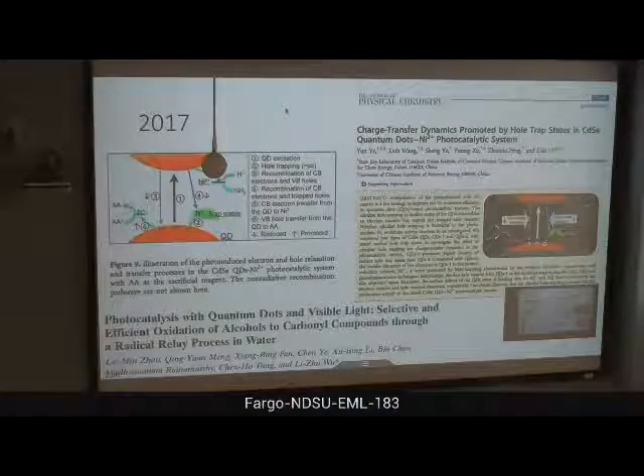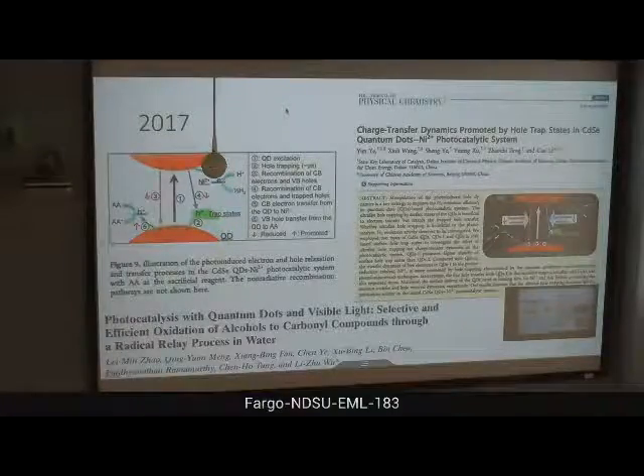But which quantum dot do they use? This one is with cadmium selenide, cadmium selenide with nickel doping, or whatever they call it. Yep, thank you. I think the diameter of the smallest, quantum dot 1, was like 1.8 nanometers, so it's still pushing close to maybe the limit for what we want to do. With the reduction of the size, the effect of the different defects within the surface increases. And so the nickel can come in, populate or physisorb to a surface defect site from the cadmium, and then enhance this type of electron transfer to the nickel.